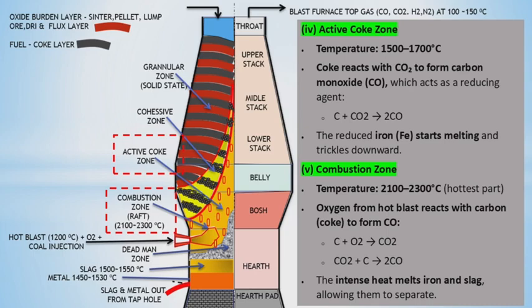Combustion zone. Temperature, 2100 to 2300 degrees Celsius, the hottest part. Oxygen from the hot blast reacts with carbon, coke, to form CO. C + O2 = CO2. CO2 + C = 2CO. The intense heat melts iron and slag, allowing them to separate.